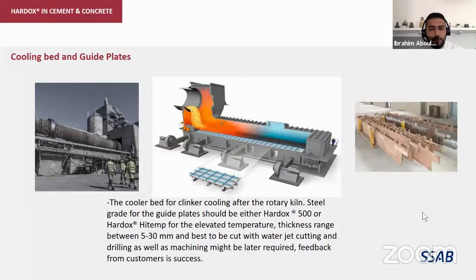Then we move to the rotary kiln. In the rotary kiln especially, we don't have a lot of applications, since, as I said, the temperature is between 1000 to 1500 degrees. The only thing we can speak about is that after the heating, there are some cooling beds in which there are some guide vanes that are dividing some flow. The temperature at that point is up to around 500 degrees, and for that we have the Hardox HiTemp.